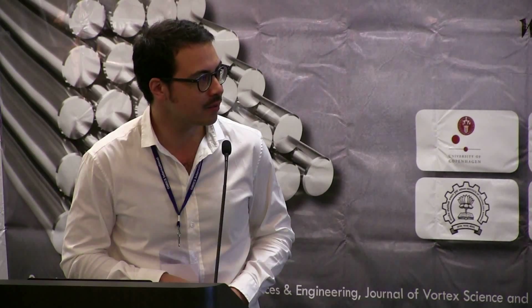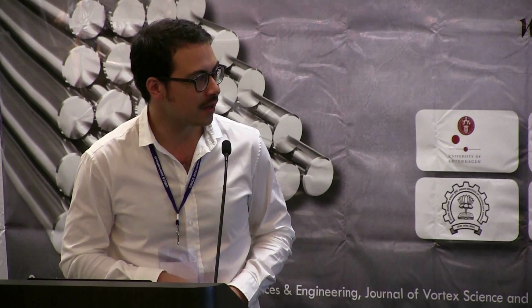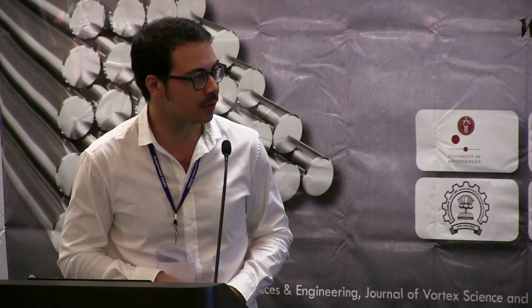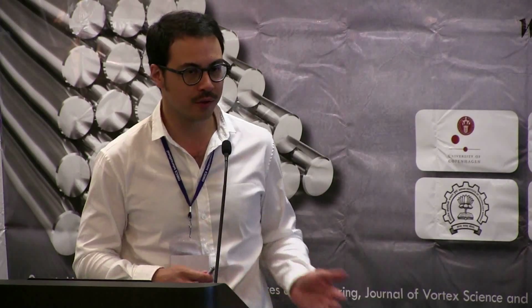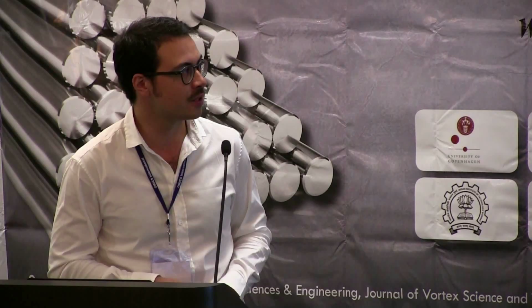We had an intermediate annealing process with protective gas and water quenched, and as the last step also a final heat treatment with 500 degrees Celsius, 20 minutes. But after that, it was followed by a SIM training. The training parameters were the same for both, for the good and for the bad wire. We had an annealing temperature of 180 degrees Celsius, annealing time of 10 seconds. So the wire from this point to this point, it needed 10 seconds. This is our tube for heating, and 80 cycles. And the training stress was about 175 Newton per millimeter squared. So the same training parameters were applied for both wires, type A and B.